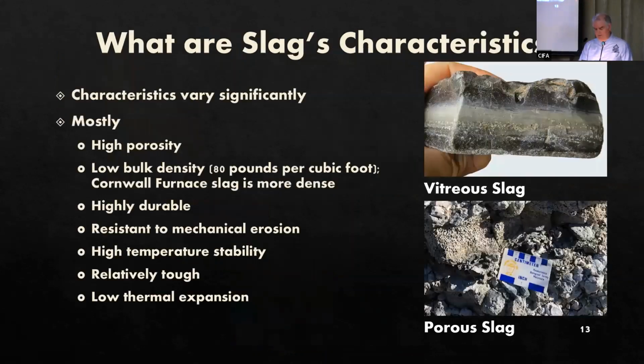So now that we've talked about what slag contains, we can discuss the physical characteristics of the slag. As I previously stated, these characteristics can vary considerably, just like the composition. One of the most characteristic features of slag is the presence of gas bubbles or voids or vesicular cavities. The voids in the slag give it a higher porosity, even though those voids may not necessarily be interconnected. But because of those voids, the rock, the slag, is less dense than most rocks. So the average bulk density of slag is about 80 pounds per cubic foot.